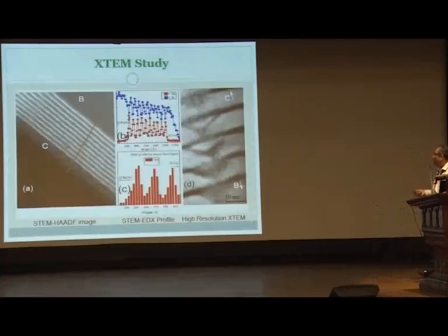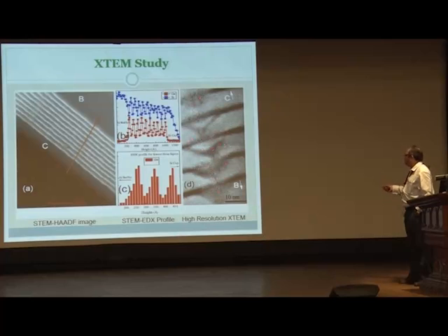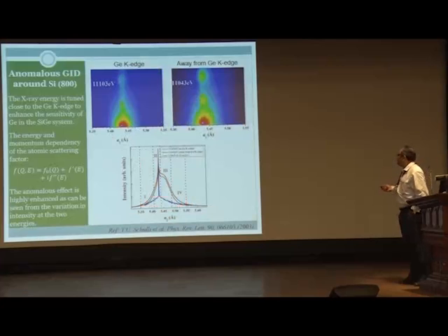Now, of course, we were interested to grow that, and finally Manjula could grow it, and by doing this silicon germanium compositional profile, we could see this. These are grown on a superlattice, and these inverted quantum dots of germanium are growing one on top of the other, which is expected. And so again, we did this X-ray scattering to find out the composition and all that.